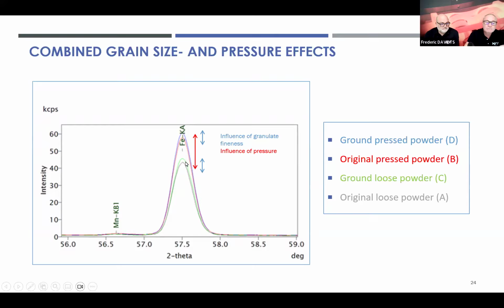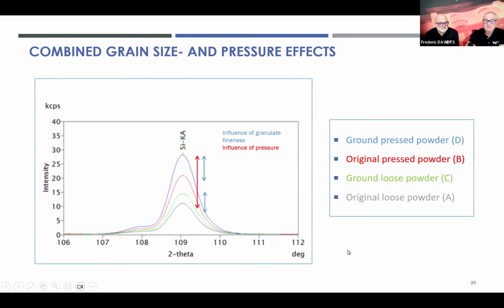Without pressing, there is still some difference between the ground sample and the original one. But as soon as we press the sample, as we have seen before, the intensity increases drastically. Silicon is even more drastic. So here we can see from 10 kcps to 30 kcps, or 3 times more intensity between the original and the ground pressed powder.